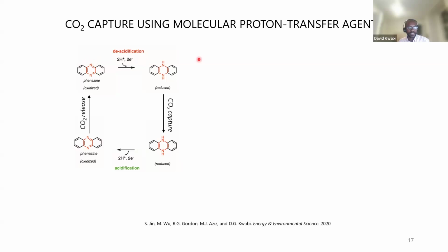So going from left to right, you can have an alkaline electrolyte. That alkaline electrolyte can capture CO2 from air, where it reacts to form a carbonate or bicarbonate. Then you can acidify the electrolyte by oxidizing the molecule. You release those 2 protons, and now you have CO2 that can be sequestered or separated as a pure gas. So we're essentially using the increased chemical stability, but also this extra potential of doing a pH swing to enact CO2 separation.